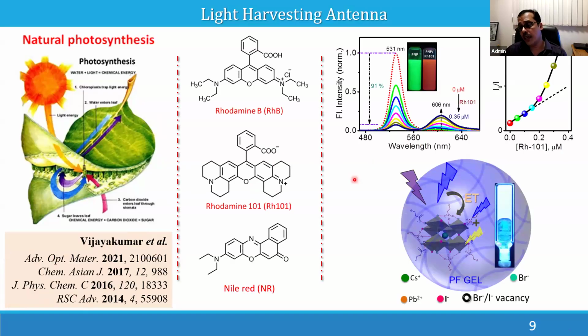So here you can see the energy transfer happening in this material. Initially we were getting a very sharp emission, which is the green emission of the material. We were using the bromide-based composition. The bromide-based composition normally gives beautiful green emission. And when we started adding small quantities of rhodamine 101, this is the rhodamine 101, you can see the emission in the green region, 531 nanometer, is quenching, and subsequently there is an emission at 606 nanometer. This quenching is of the emission coming from the nanocrystals, and this is the emission coming from the fluorophore, that is the rhodamine, that is the acceptor, energy acceptor chromophore.